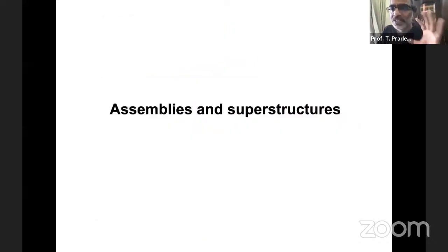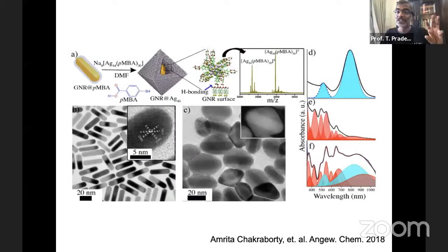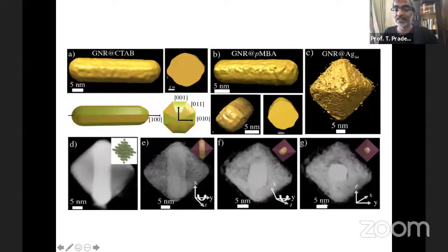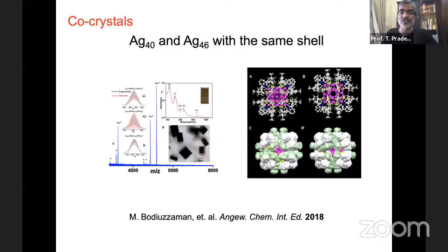But it is not only that you can study these fundamental things. Using these clusters, you can assemble them on plasmonic systems, such as a gold nanorod, and you can create such systems of this kind, which will combine plasmonic properties with the properties of individual clusters, as shown here with optical absorption spectroscopy. Gold nanorod and the cluster and the composite system together. You can also image this in greater detail, reconstruct the structures.